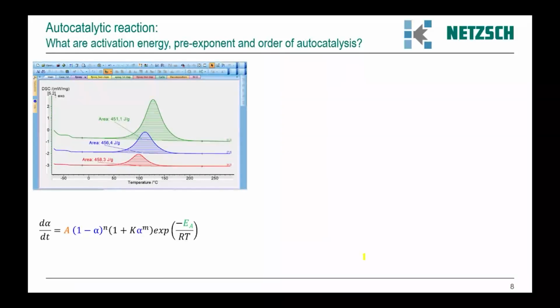Next question: we have autocatalytic reactions. What are the activation energy, pre-exponent, and order of autocatalysis? Now, it should be an autocatalytic reaction, for example for curing. Here is epoxy curing. We have n, the reaction order, we have the activation energy, we have the order of autocatalysis. Here is the pre-exponent for autocatalysis.